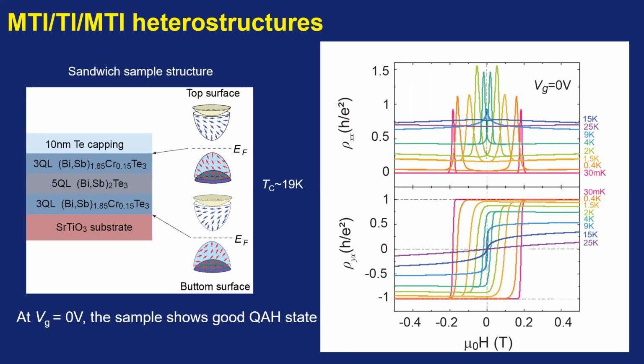This is the transport result of our sample. We can see at 0 gate voltage at the base temperature, 30 millikelvin, it shows a very good quantum anomalous Hall state. It's quantized and the longitudinal resistance is below 10 ohm. And when you increase the temperature, the Hall resistance shows this kind of hysteresis loop, and the magnetoresistance shows this kind of butterfly structure. These are just the typical phenomena of a ferromagnetic material, and the TC of this material is about 19 Kelvin.